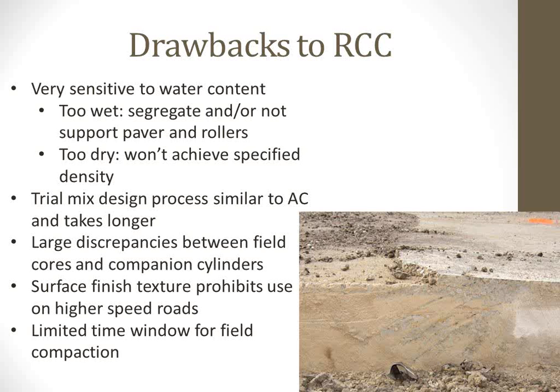It's a rough surface, as you can see on the right, so it's typically only used on low-speed roads or parking lots, and it's typically about a 45-minute window from when mixing starts to when you can compact it. Otherwise, we get this. It's deterioration and spalling at the joint, as well as cracking after, I think this was 2 days after placement.